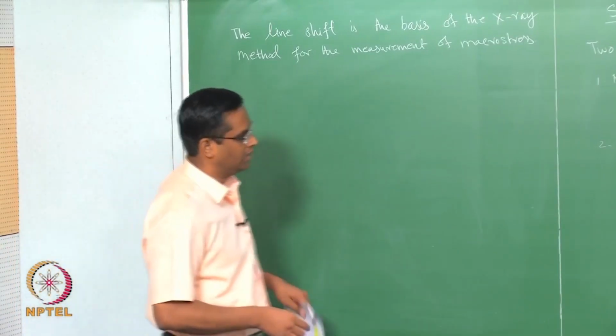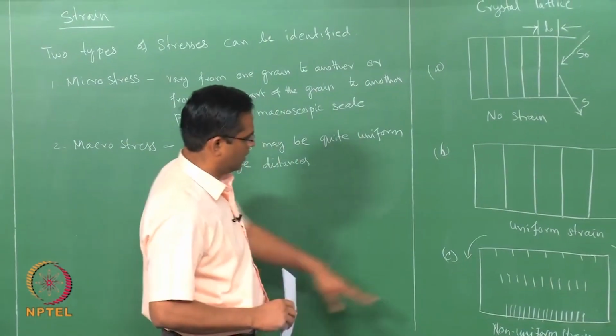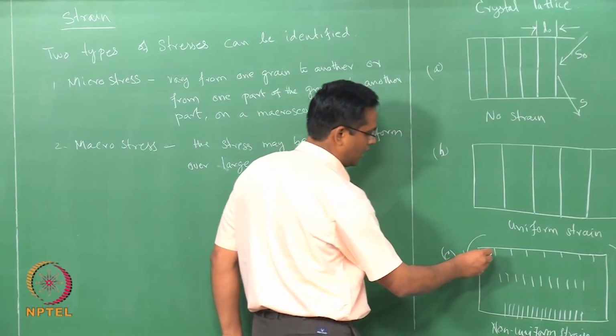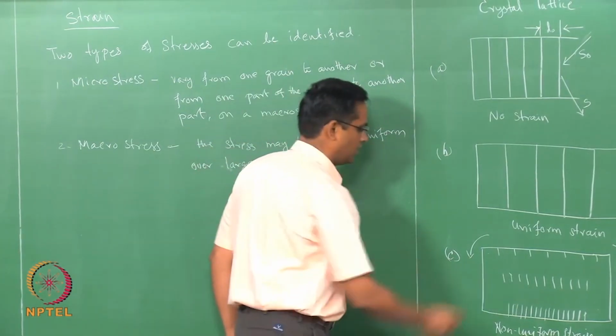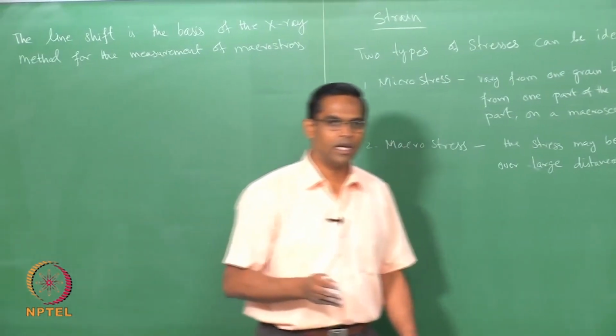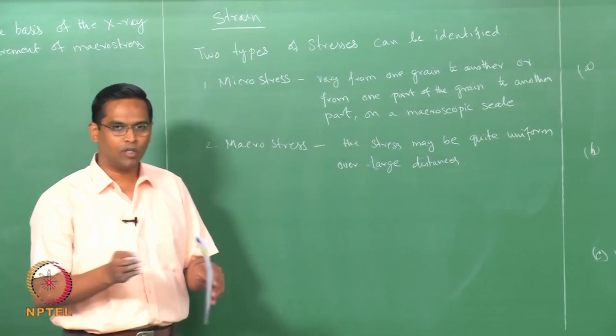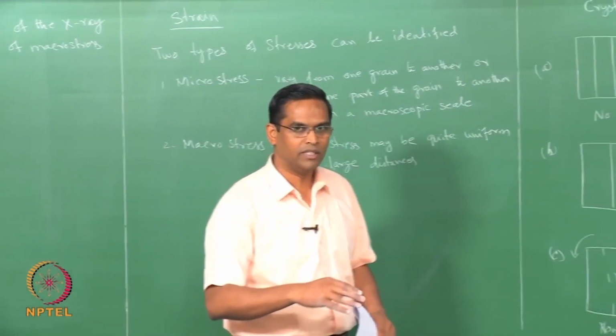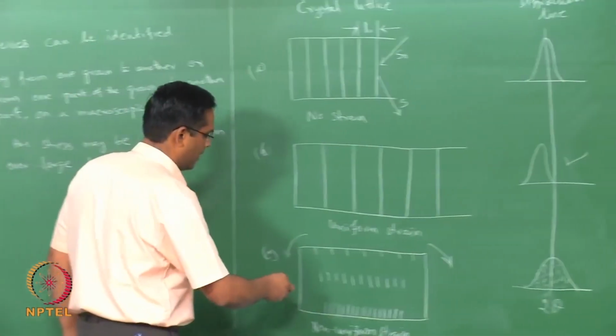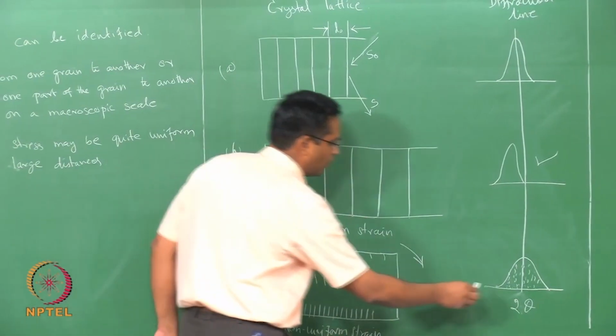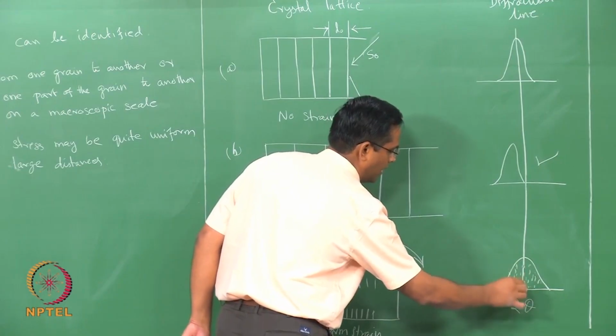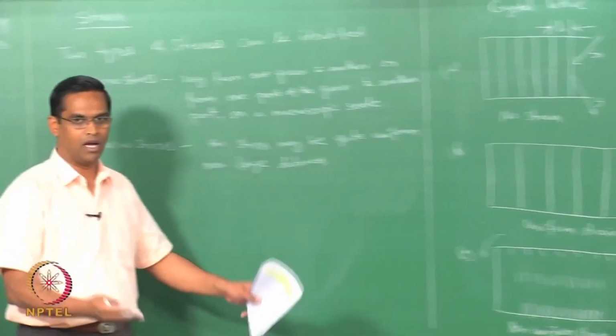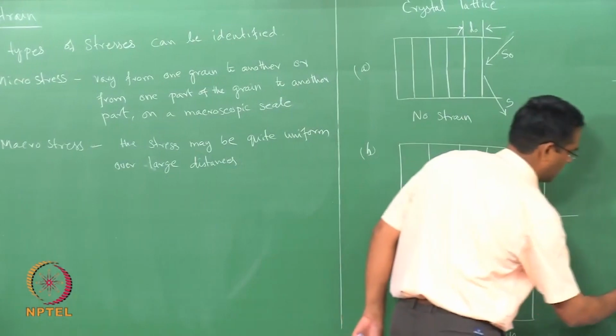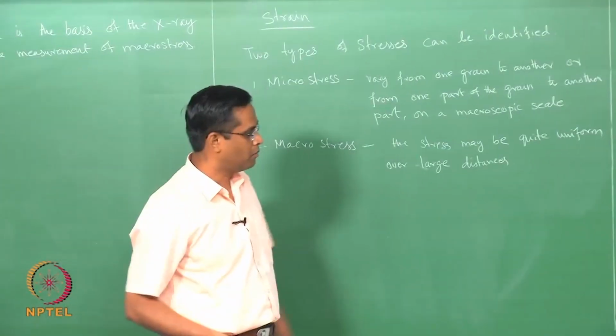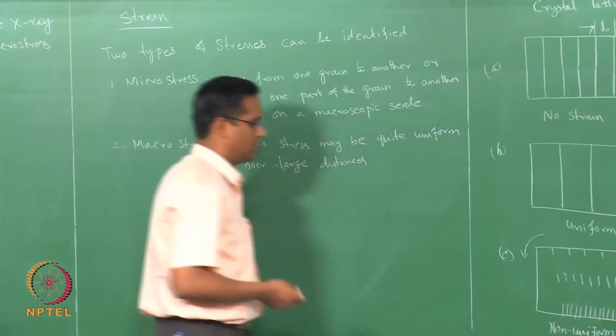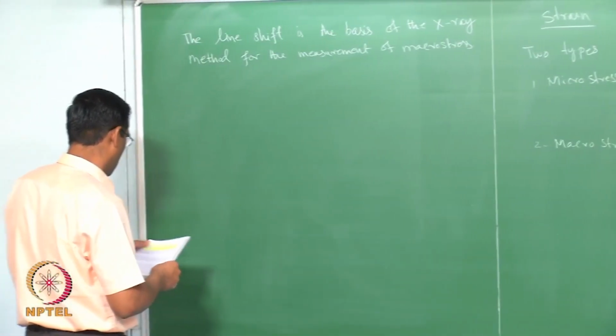And then, like I said, in this particular case where you have d more than d naught, and here d is less than d naught, and somewhere in between it is equivalent to d naught, you will have a region in a grain where the d spacing is constant with respect to the neighboring region within the grain itself. Because of that kind of situation, each one of these will produce a small sharp peak inside, which eventually we observe or record as a broad intensity peak. That is why you see this as a very broad intensity spectrum, and we will now see how we measure this.